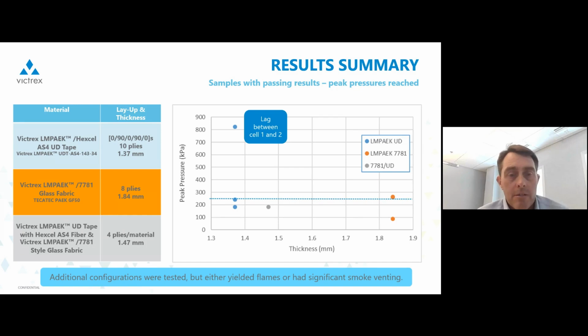But if you think back to that slide that had a bit of a knee, or a bump in the curve, where the battery cell was failing, and the trigger cells were failing, there was a bit of a lag between cell 1 and cell 2. And in that particular test, the peak pressure measured was actually about 824 kPa. So significantly higher than the other tests, but passing nonetheless.